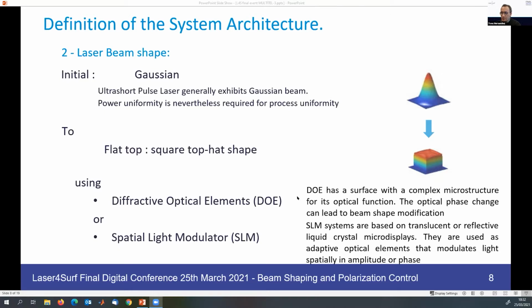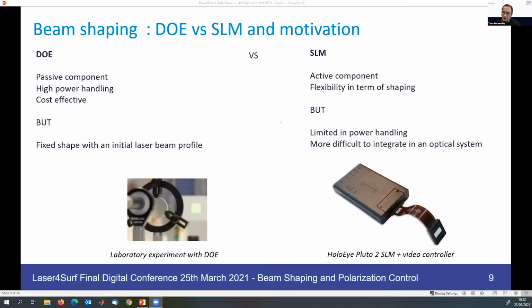We have two main options for getting top hat beam, which is to use diffractive optical elements or spatial light modulators. And actually in the project we tested both options. Why? The reason is that each solution has its own advantages and drawbacks. If you use a DOE, it's a passive component. It's quite compact. It's easy to handle. It's easy to integrate. It can sustain very high power. But the drawback is that it has a fixed shape.